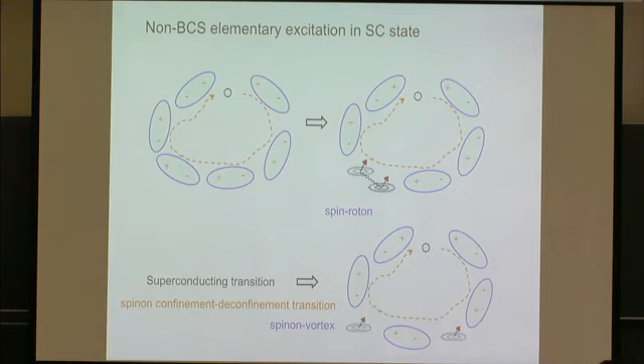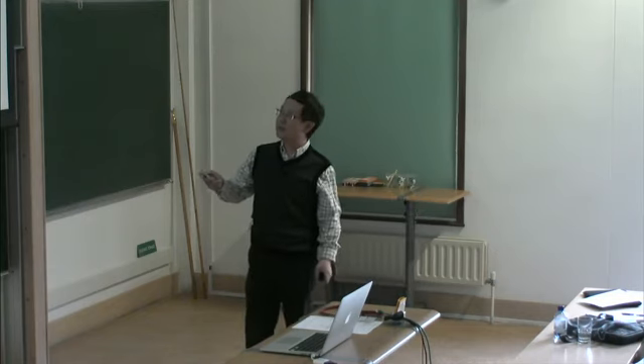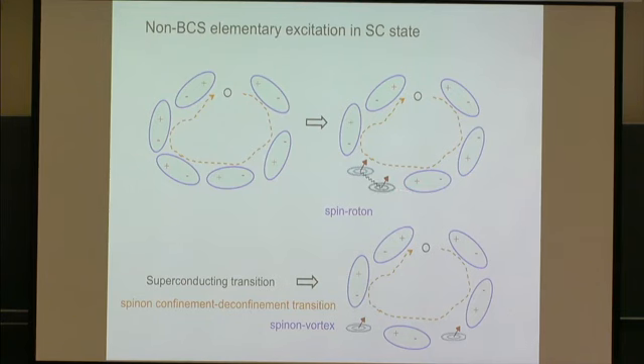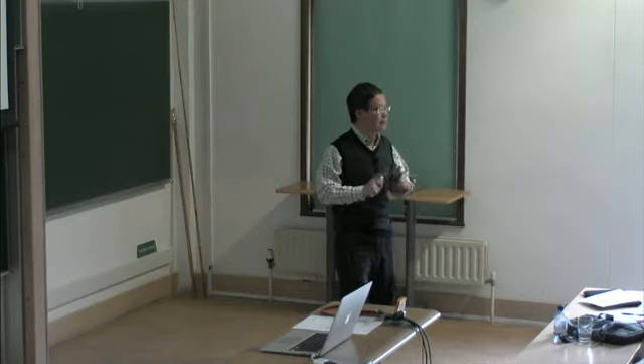And this is a way to ensure that superconductivity is stable over a finite temperature range. In other words, you can make the superconductor decohere, a phase transition, by making this bond pairing deconfined. Once you have free spinons here, it really becomes no longer a superconducting state. So we have some kind of spinon confinement-deconfinement transition coinciding with the superconducting transition. But this confinement is very weak.